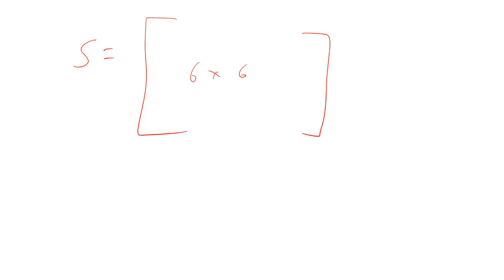But is this 6x6 matrix a tensor? No. It's a way of representing a fourth order tensor as a matrix. So can you transform S as the matrix? Basically everyone went S prime equals Q S Q transpose, and this is not true in any way, shape, or form.